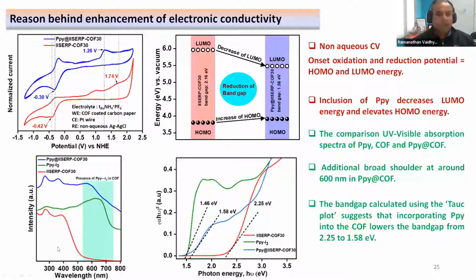electron volts. The same can be observed also from the UV visible spectra, where we calculate using the Tauc plot the band gaps, and you can see the band gap of the neat COF is 2.25 electron volts, which comes down to 1.58 electron volts upon loading the electronically active polypyrrole chains.